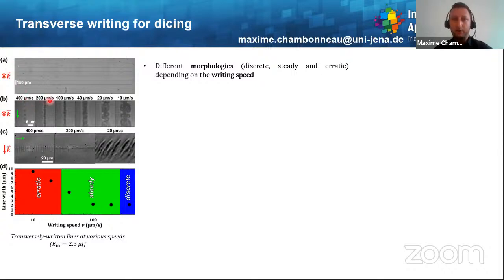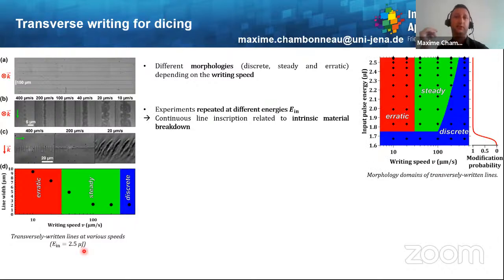And the line morphology can be discrete, steady, or erratic, mainly depending on the writing speed. Here the input pulse energy is constant at 2.5 microjoule. We repeated this kind of experiment at different input pulse energies. Here is the input pulse energy on this axis, and the writing speed. The black points represent some tested configurations, which allow us to discriminate different domains for the line morphology.